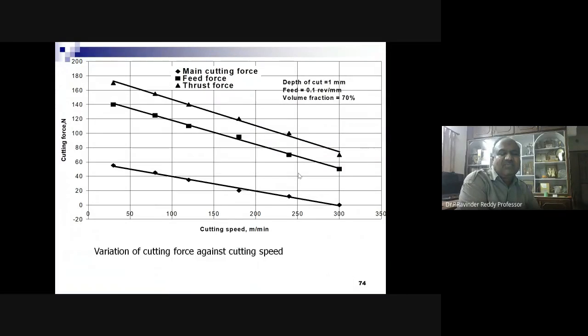The cutting forces, when you measure against cutting speed, it's a different kind of observation you can make. So the main cutting force, feed force, thrust force, these forces are in the order given here. With cutting speed, generally contact is increased, rubbing is there, cutting force is supposed to increase, but surprisingly here, the cutting forces are reduced. These experiments were conducted at depth of cut 1 mm, feed 0.1 mm per revolution, the volume fraction at 70%.